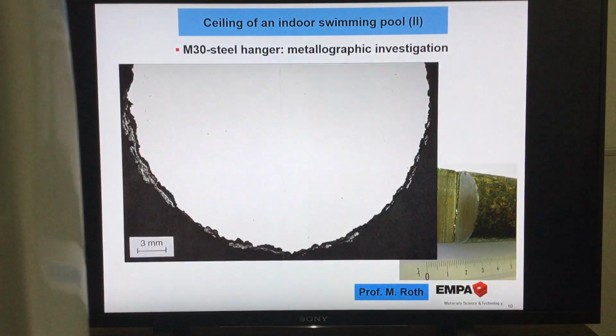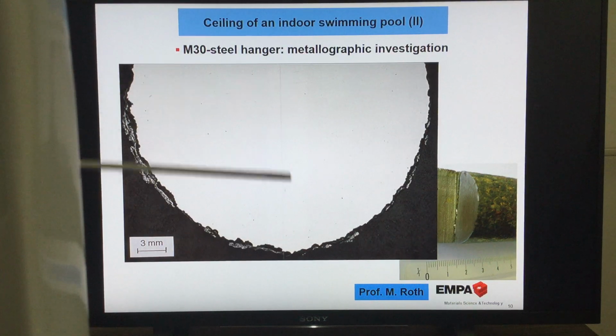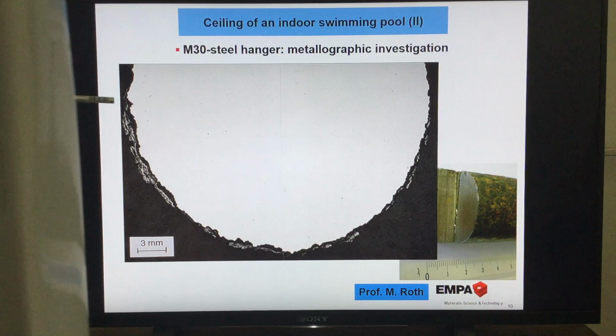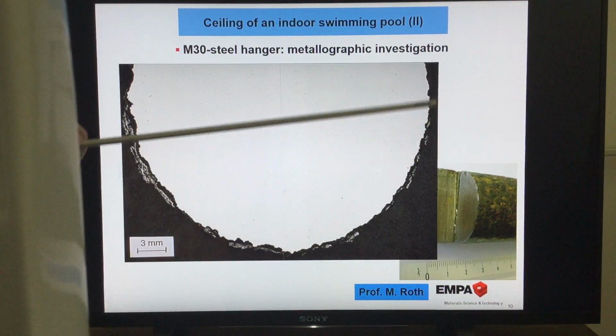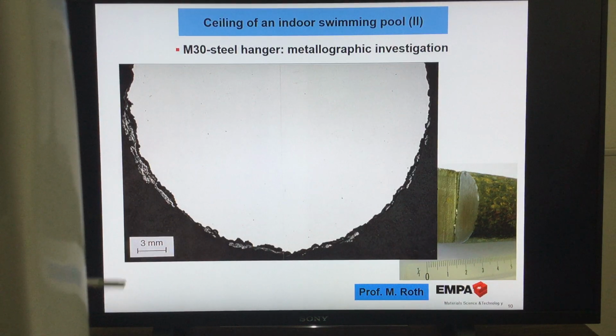Now the next slide is very important. It shows you now the whole diameter of our steel hanger and this cut here. And you see here the inside, it's again just white. You see no cracks inside. That is our base material, and around you see the oxide layer. Around the oxide layer, you see here the scale, it's 3 millimeter.